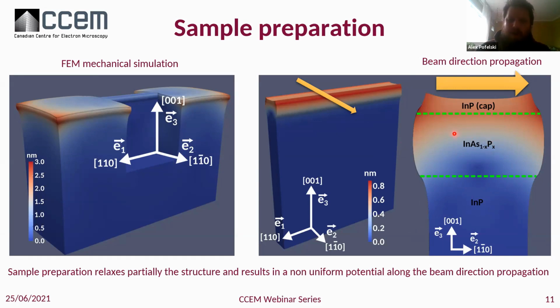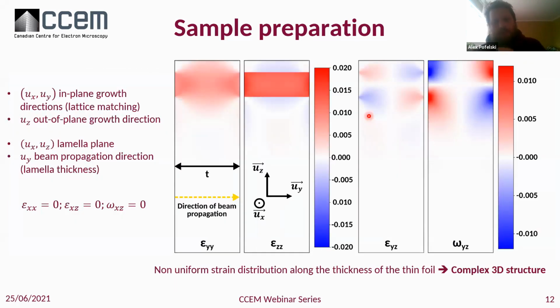But the second important part is that the deformation is not uniform along the beam propagation direction. So this already raises some questions about what exactly the beam propagation is measuring inside, because we have a 2D projection of this 3D complex structure. But in any case, if we just look at the simulation part, this is the result that we're going to keep in mind.